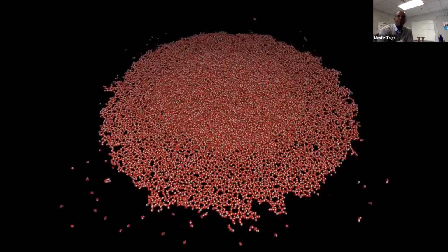The reason being, when we prepare polymer systems, they are usually in close proximity with air, which is hydrophobic. And if our polymeric system has both hydrophobic and hydrophilic groups, in the process of making the film, mostly the hydrophobic groups come in contact with the surface. Now, when you put a water droplet on top of that surface, initially you get a higher contact angle, but over time, you start to see the contact angle decreasing, because the hydrophilic groups start to orient to the surface because they see water is coming in contact, the hydrophobic groups avoid, and then you start the water droplet completely wetting the surface.